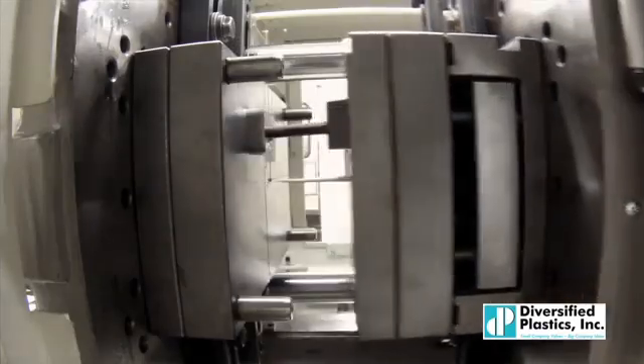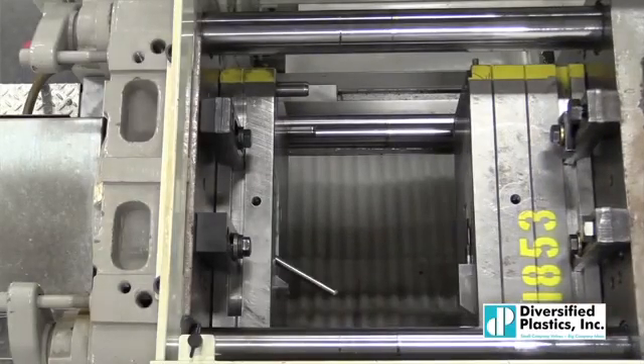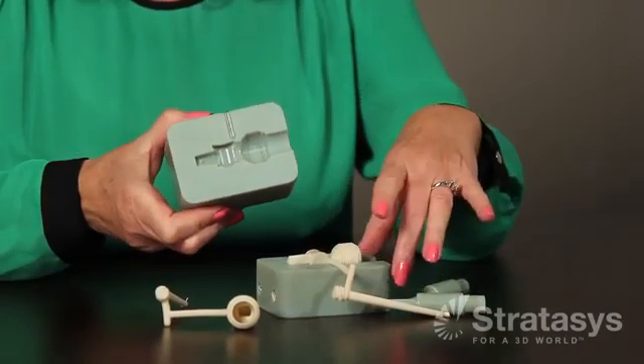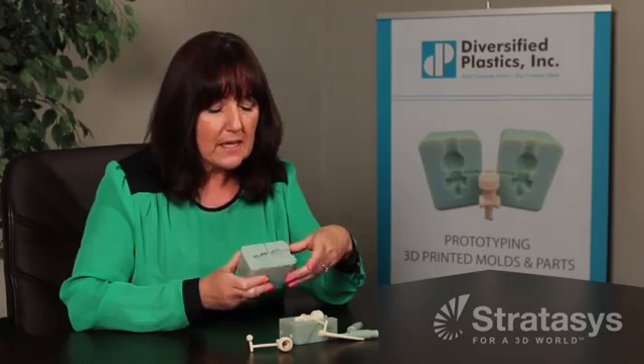When we're looking at comparing costs between the 3D printed cavity and core blocks versus a P20 tool steel, which we would usually use in a prototype process — printing the product using an existing mold frame for this particular core block and cavity is about $1,800. If we were going to do it in P20 tool steel, it would be closer to $10,000. We have found with experience that it is the way to go, especially on a thermoplastic elastomer.